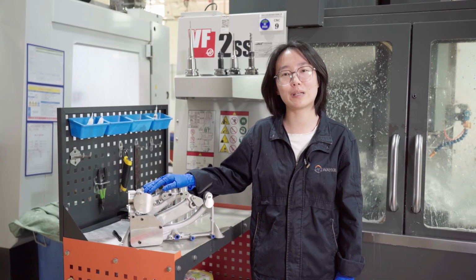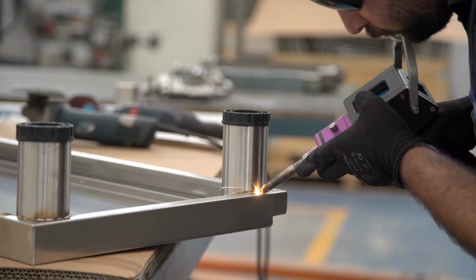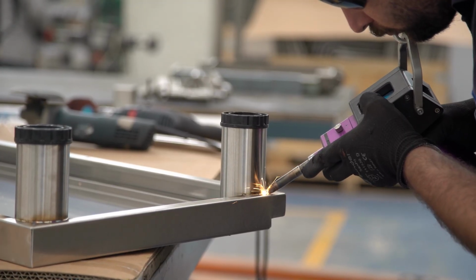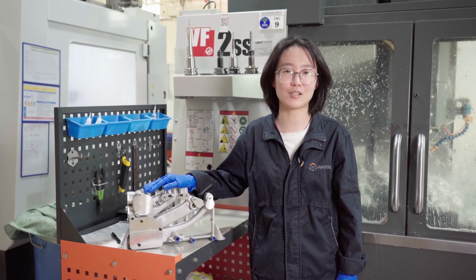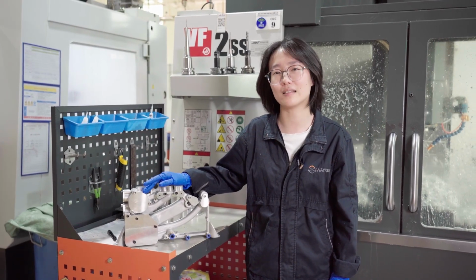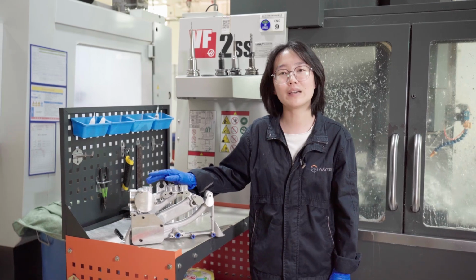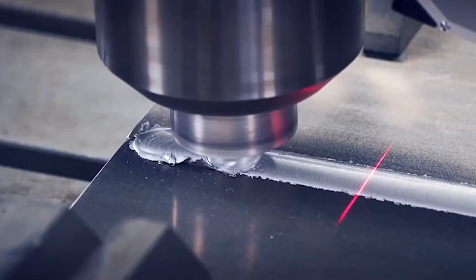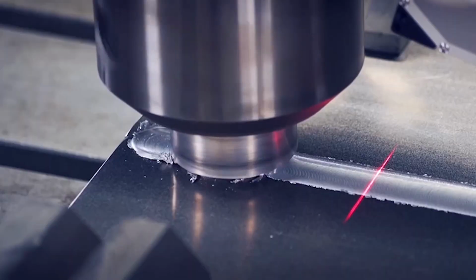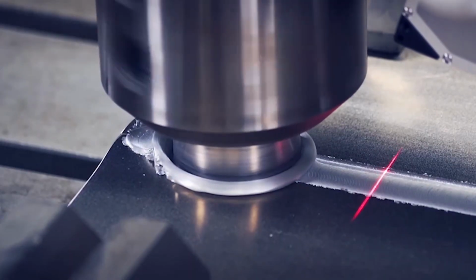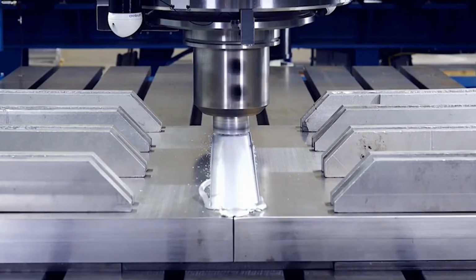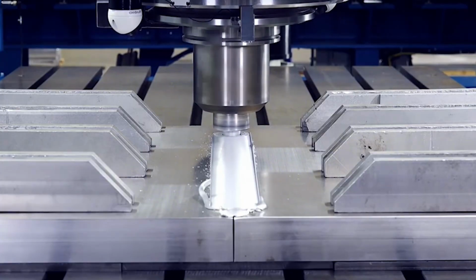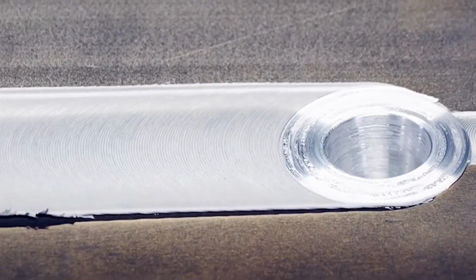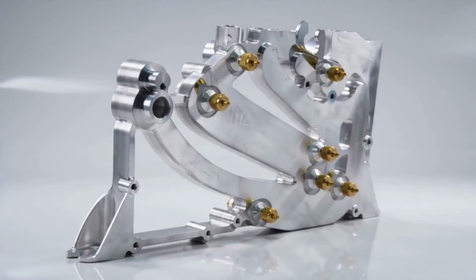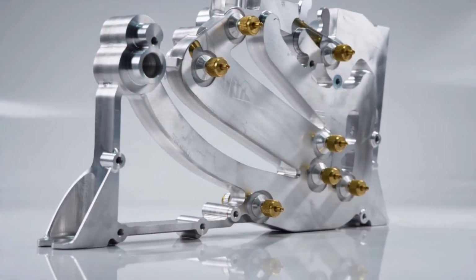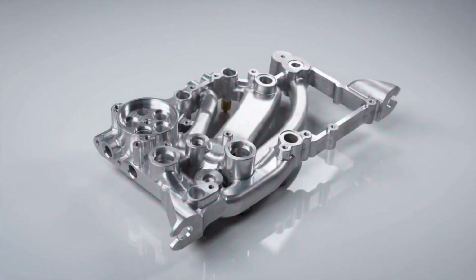But conventional welding has 2 issues: large welding seams and a large heat affected zone. Air tightness is difficult to guarantee, and flatness is hard to control. We can use friction welding. This is a solid-state joining technology with a small heat affected zone. No porosity or slag inclusions, weld strengths close to that of the base material, and controllable deformation. Both air tightness and flatness achieve the customer requirements.